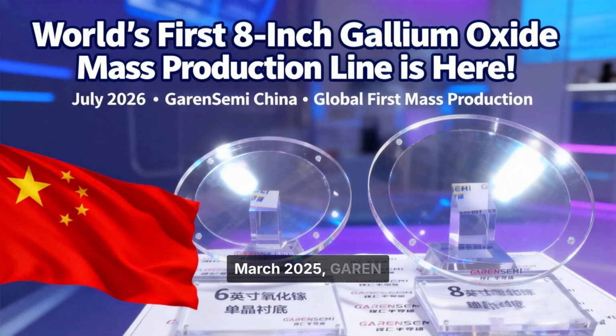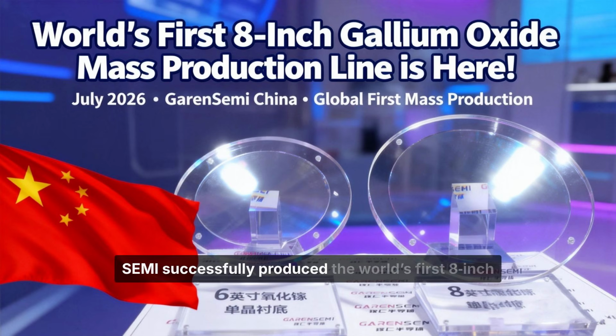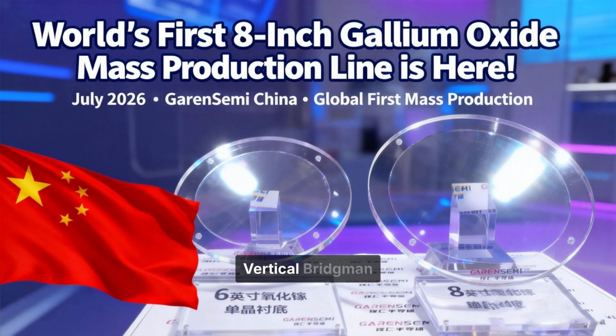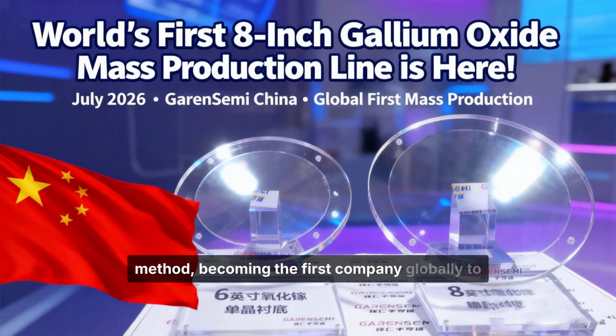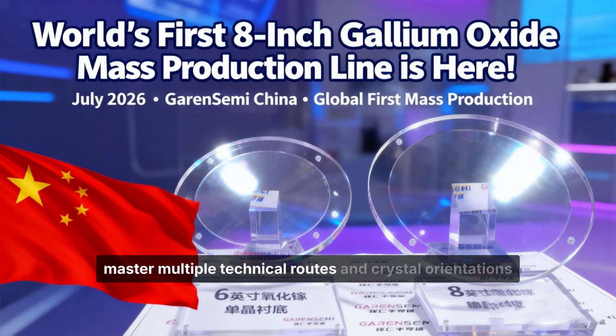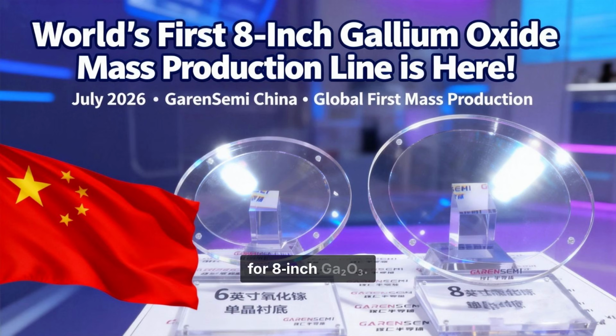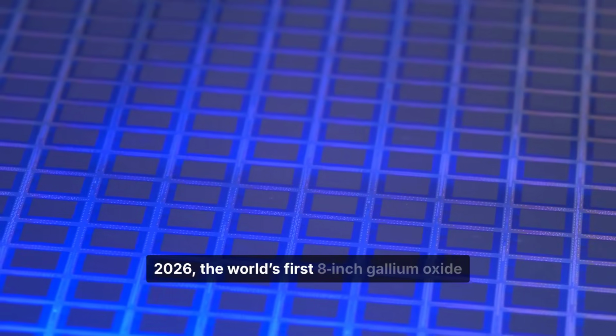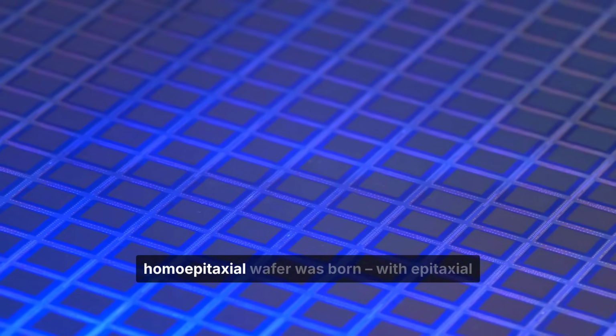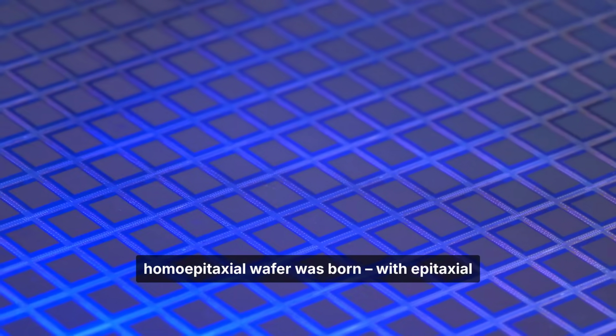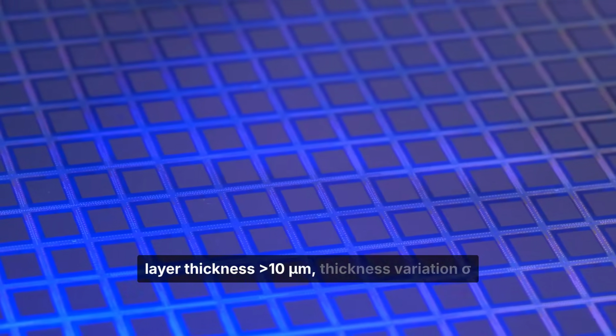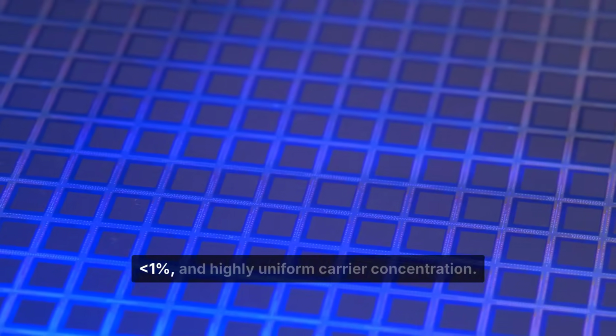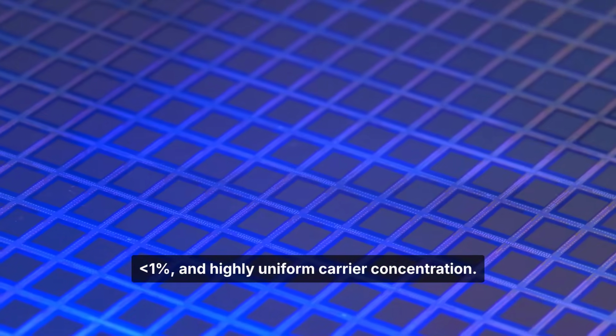In March 2025, GAREN SEMI successfully produced the world's first 8-inch gallium oxide single crystal. Later, they also achieved 8-inch growth using the vertical Bridgman method, becoming the first company globally to master multiple technical routes and crystal orientations for 8-inch Ga₂O₃. In March 2026, the world's first 8-inch gallium oxide homoepitaxial wafer was born, with epitaxial layer thickness variation ≤1%, and highly uniform carrier concentration.